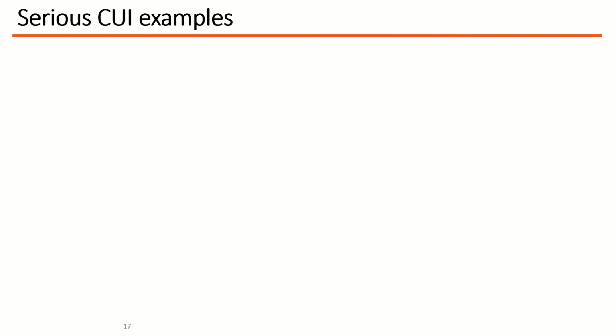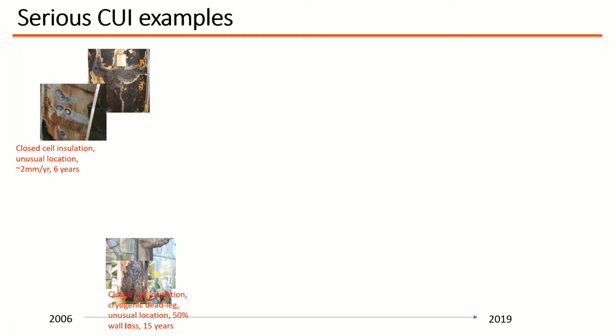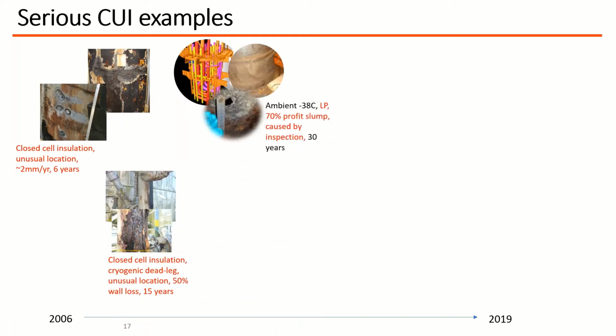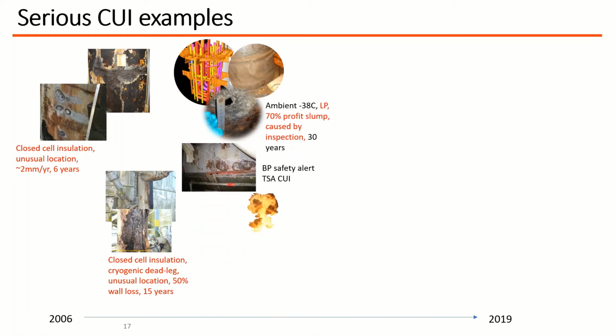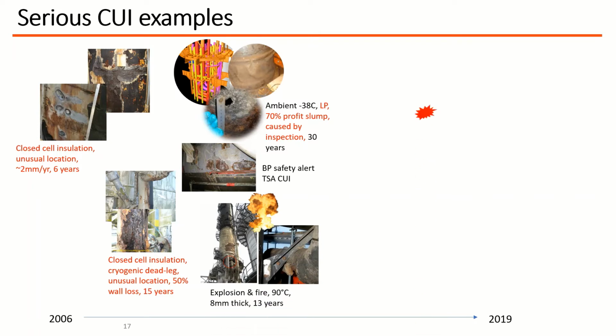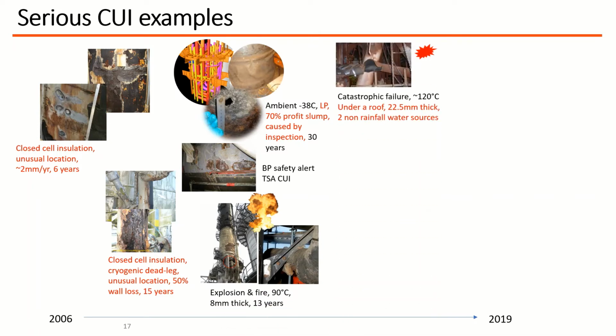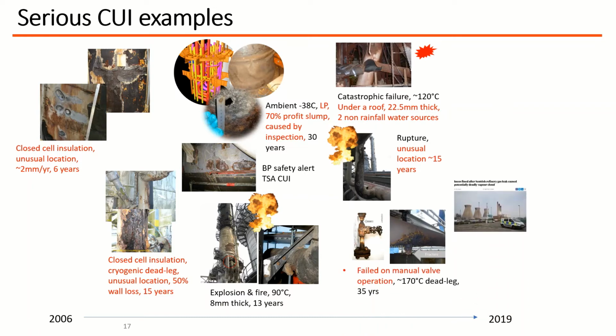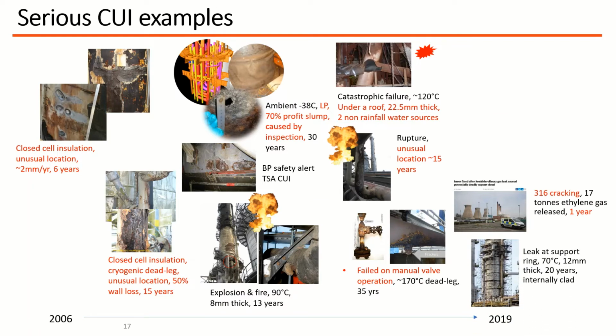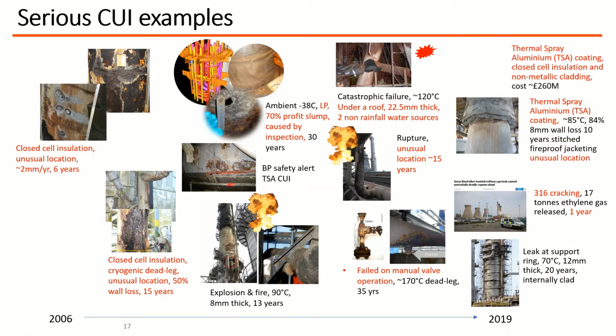So I'm just going to, with this slide, click through some of the serious CUI inspection findings and failures that we're aware of that occurred over the last decade or so. And I'm going to try and speak about them in a general way while I'm introducing them to the slide, which is quite difficult. So the first thing we notice is that they occur for different temperatures, over different timescales, for materials of different wall thickness and different designs. And all of them, or the carbon steel ones, relate to failures that occurred or would have occurred after 10 years in service, a lot of them after 20 years in service. But to avoid economic impact, you often would have needed to inspect well before this.